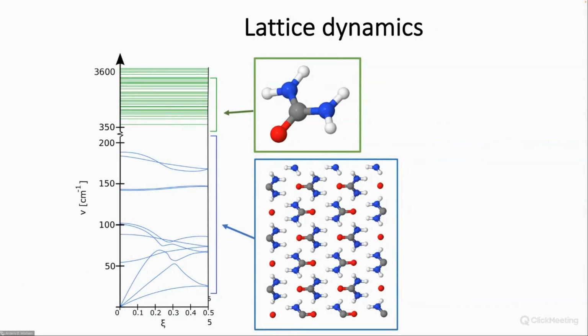So what is it that we are doing here? We are taking a plot of the dispersion relations in one compound, urea, in one particular direction of the Brillouin zone, and we can divide the different lattice phonons into two regimes. You have the low frequency regime that contributes the largest to the anisotropic displacement parameters, and those a little up here, which are the internal modes. I can show it here by starting these small movies.